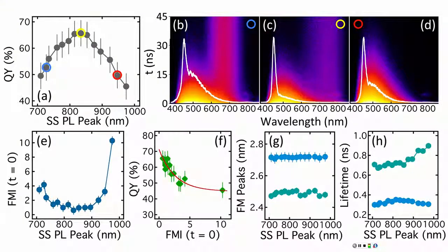It's very, very weak. Wait, what is the time range for your integration? 45 nanoseconds, and then we go from basically 100 nanoseconds out to a millisecond. We have two different detectors. So one is probing this, which is really, really slow because it's indirect. It's got to wait around for a phonon.